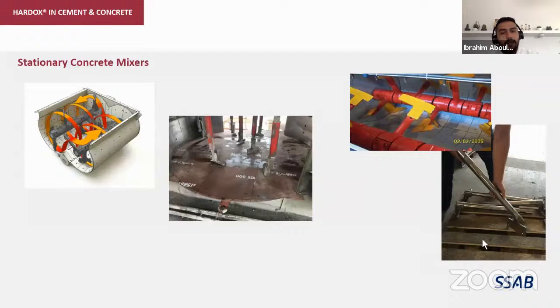Ni-Hard materials are very, very expensive, more or less the most expensive material when it comes to wear resistance worldwide. And comparing the service life of the Hardox 600 with the Ni-Hard, we have 50% increase in service life in the paddles, 50% increase. And you have more or less 80% decrease in cost. So Hardox 600 in that application is also great and performing quite well. Next slide, please.